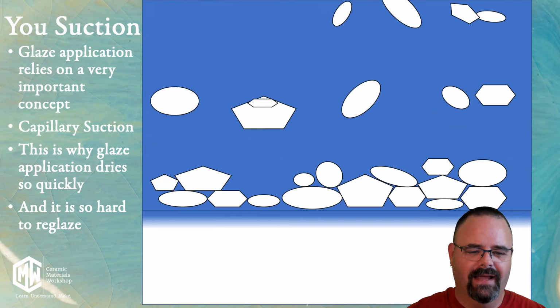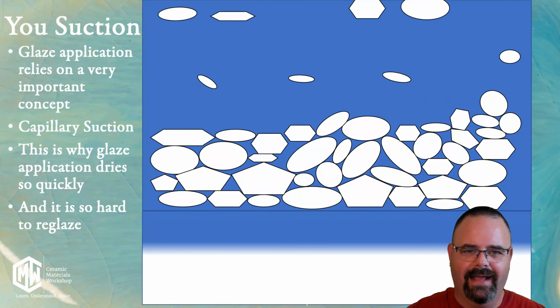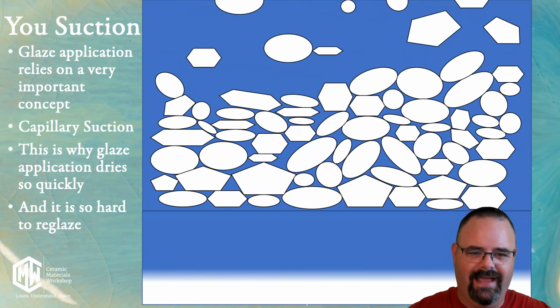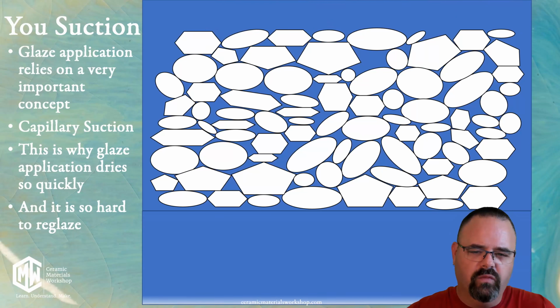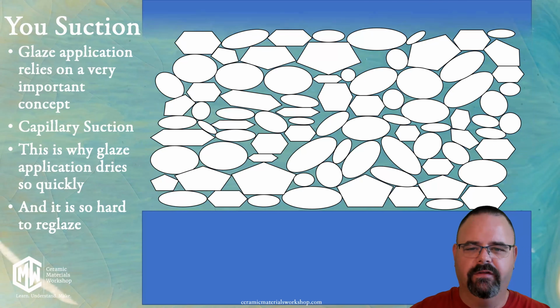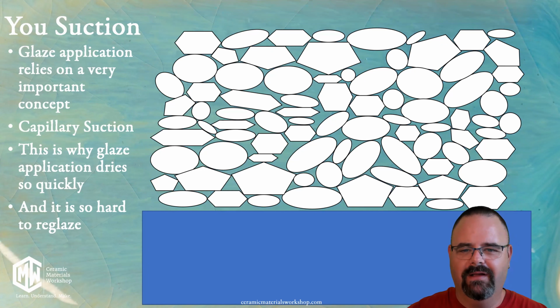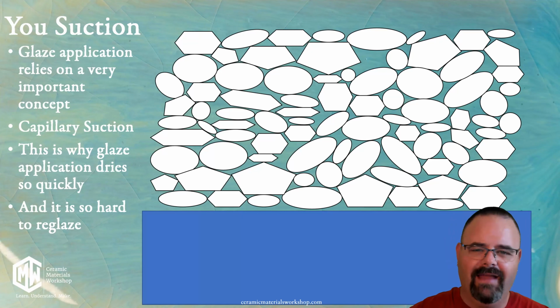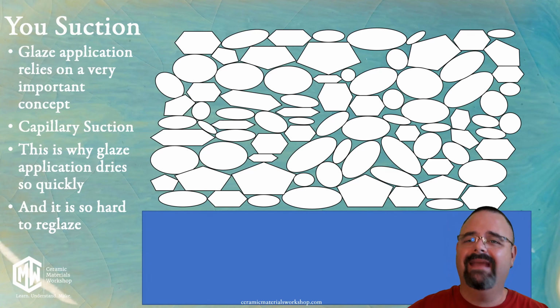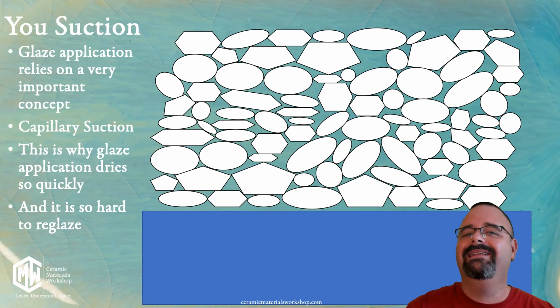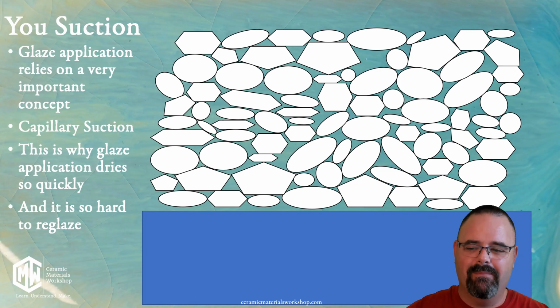So we dip our pot in glaze, and then what happens is that the clay body at the bottom starts sucking in water through this capillary suction. And as it draws water in, it's pulling glaze particles to the surface. We then remove the pot from the glaze, and then the particles stay behind, but the water continues to get sucked into the clay body until the glaze is completely dry. That's why if you've used a dipping glaze, they tend to dry within seconds, almost seeming instantly dry by the time you pull it out, or very soon thereafter. And that's because the water didn't evaporate. It went into the bisqueware.